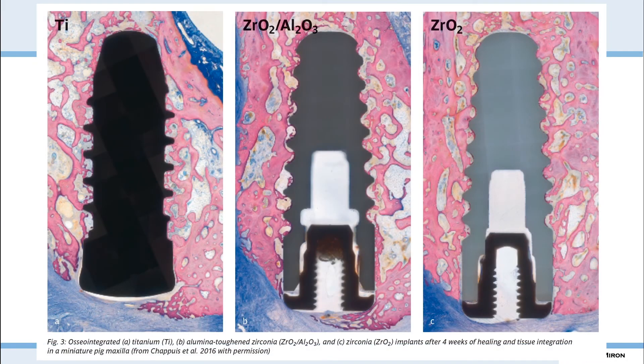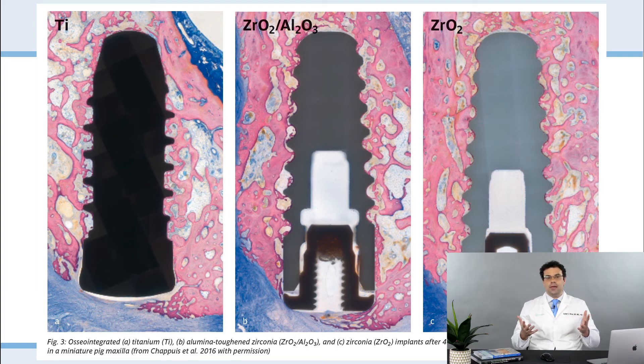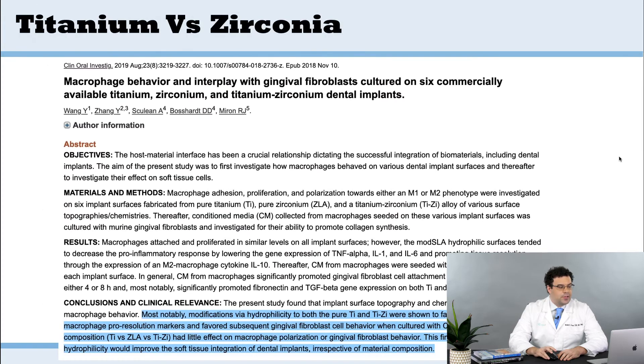I want to speak about the work that his group has done, because they've really looked at integration of titanium, integration of zirconia, and what the differences are. A lot of studies are available from the group in Bern, Switzerland, and I highly recommend people read them. Long story short: zirconia implants typically integrate at similar rates to titanium. Are they as good in bone? The answer is yes — maybe slightly less — but overall, if you use the right systems that are properly roughened, these implants integrate equally as effectively.